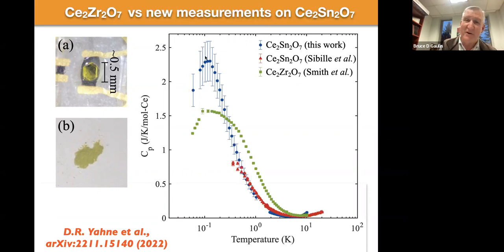And yeah, there are large error bars here, but those error bars are entirely connected with an uncertainty in the mass of the material. So if you can move the whole thing up and down, but you don't move the individual points up and down, if you see what I mean. And of course, this data actually agrees very well with the earlier data by the PSI group, by Sibille et al., that didn't go down to as low a temperature. And all of it is actually very different, surprisingly different from cerium zirconate.